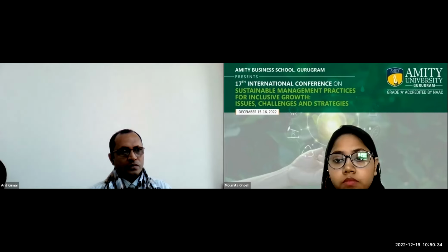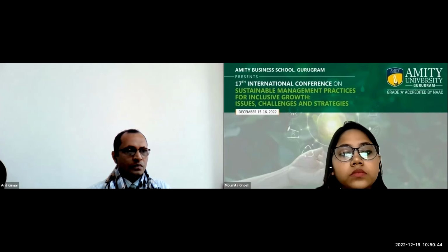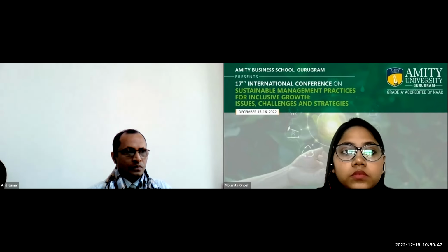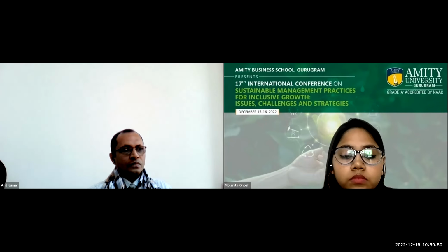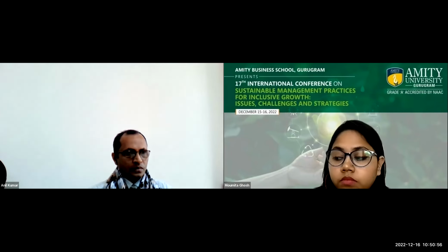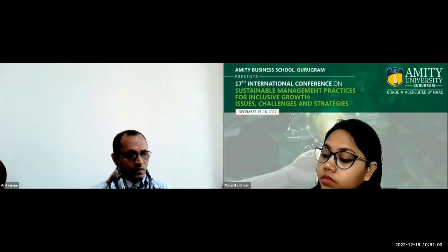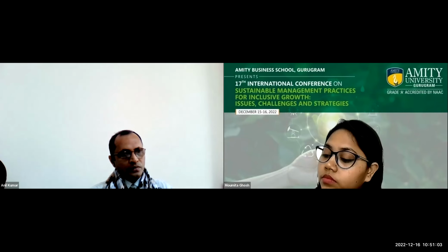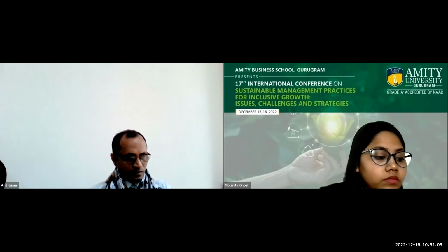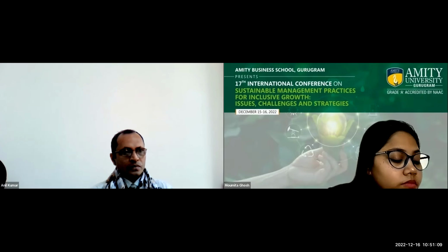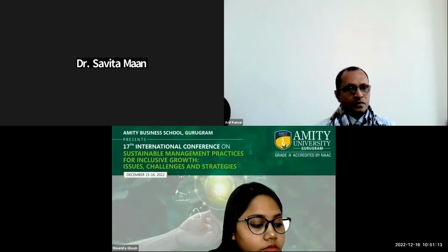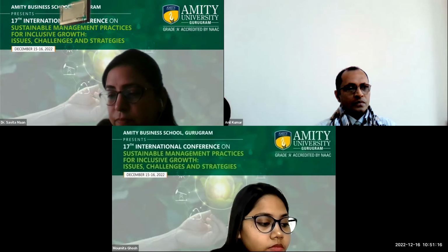If you talk about achieving more sustainability, then it has been found that rice husk ash is a potential material which is a very rich source of silica. If we can extract the silica from rice husk ash, and if we use that extracted silica in combination with sodium hydroxide for making the alkaline liquid, then it is likely to have potential utilization of rice husk ash, which is likely to cause environmental threats. Apart from that, we will achieve the geopolymer there, and it has been found that with the successful utilization of rice husk ash, we can achieve positive results. So I can suggest the use of rice husk ash as a source of silica is a good option to achieve sustainability.